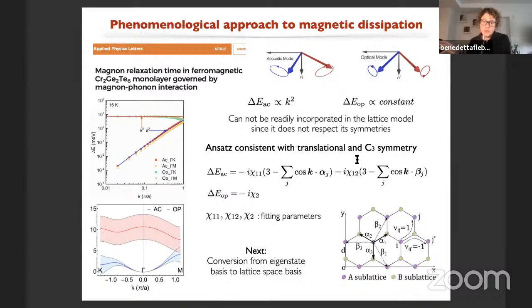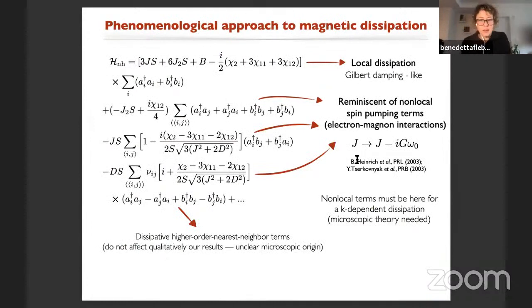So we took these terms from the eigenvector representation, and to try to make more sense of them physically, we changed our basis and went back to the sublattice real space basis. So this is the Hamiltonian in that form. There are many terms. I would say it is better to focus on this part than on all the details of the multiplicative coefficients. In few words, we find some terms that just express local dissipation. So this is a simple Gilbert damping-like term.